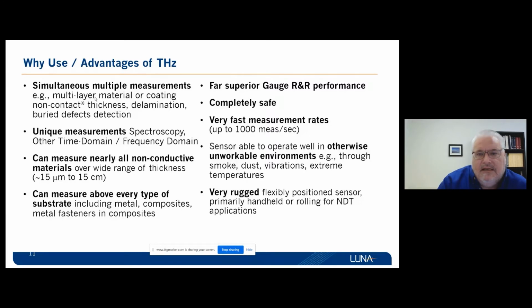It is unlike radioactive methods or X-ray methods. There's no radiation involved, no ionizing radiation. Again, unlike ultrasound, you don't have to contact. If you are doing eddy current gauges or magnetic measurements, it is not sensitive to curvature of the substrate or the substrate material, so you don't have to calibrate a witness coupon, say, for measuring the thickness of materials.